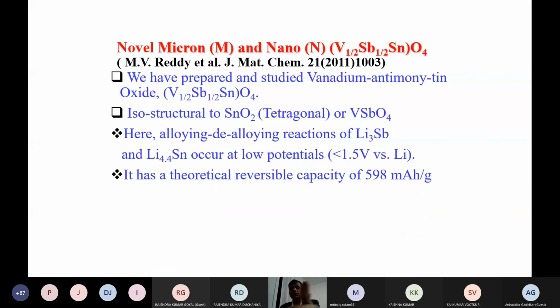So one of the new compounds we have reported is, again, because VSbO4 is already reported. That's why sometimes we can get some idea from the literature. Again, why don't you look into the antimony? So we reduced to a tin-containing oxide, because it is also a tetragonal isostructural compound. You can try to prepare it by using this approach.